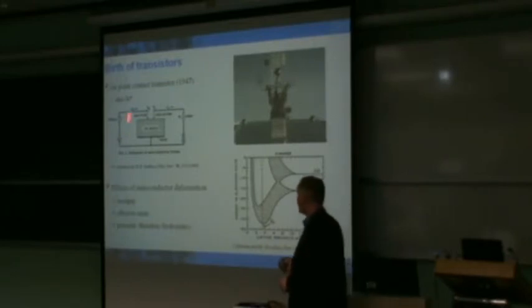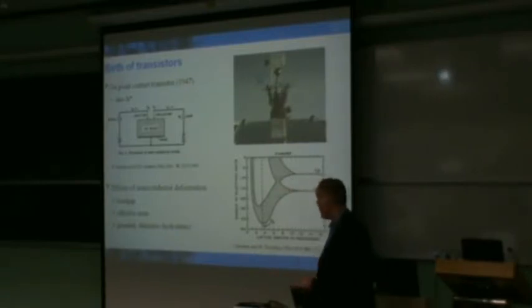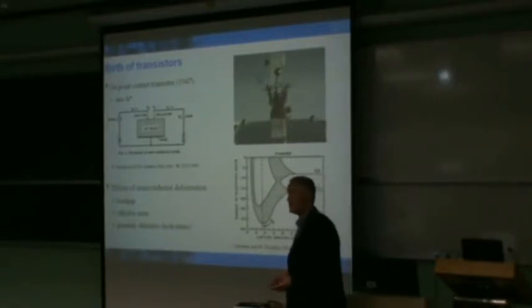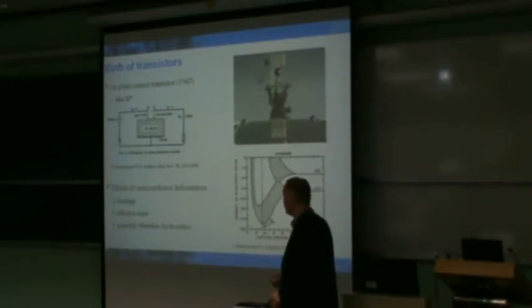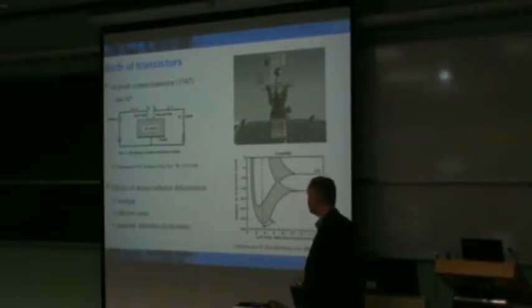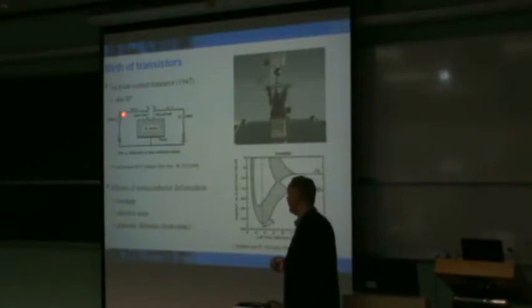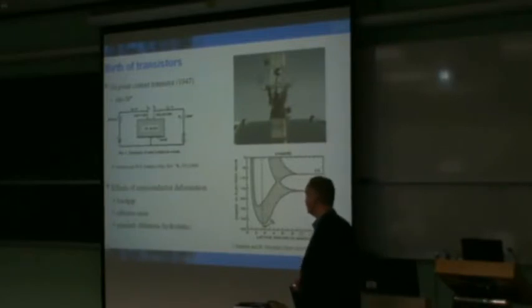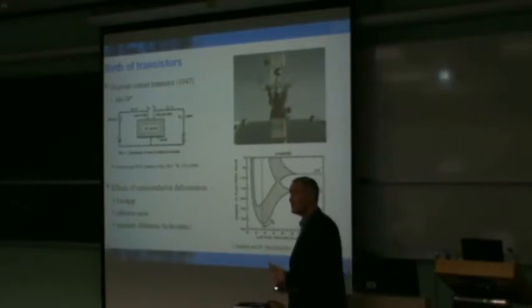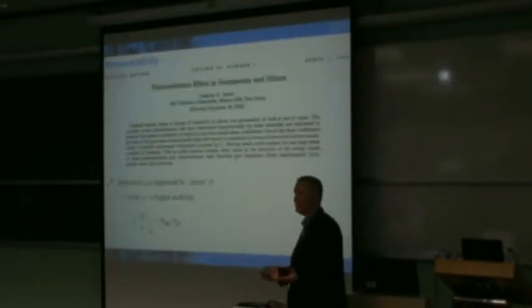The first is the fact that silicon has a very, very nice oxide that passivates, but also is not water soluble as compared to germanium. So that was one of the key aspects that led to its development. The other aspect is, as these materials were being designed for certain applications, the high temperature performance of germanium was inferior to that which silicon possessed. So those were the two aspects that really helped to drive the industry to the tens of billions of dollars that we have invested in silicon research.